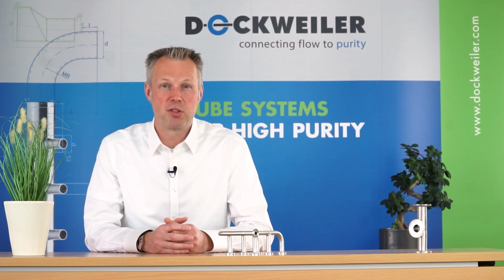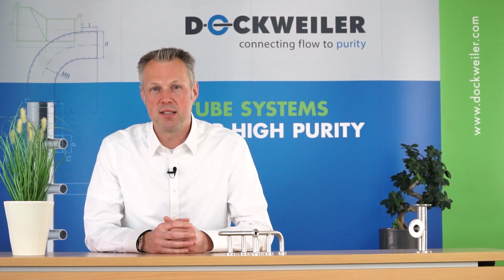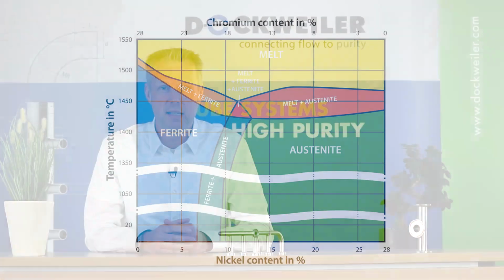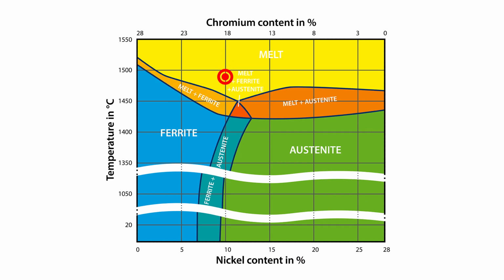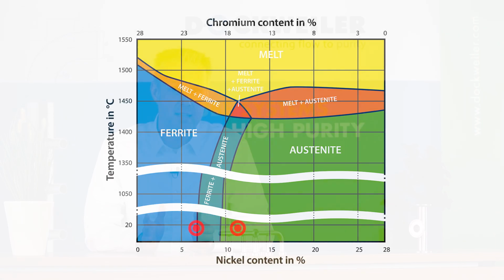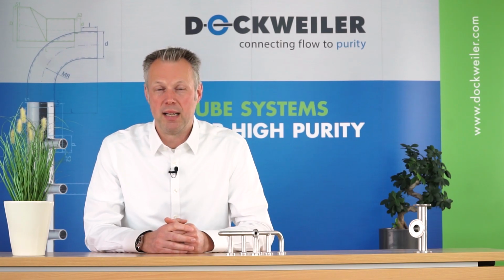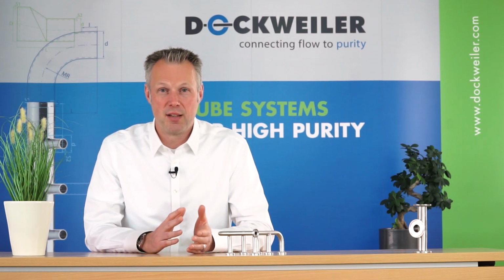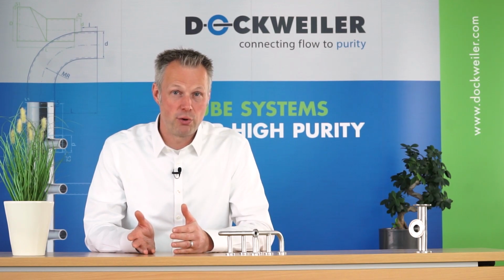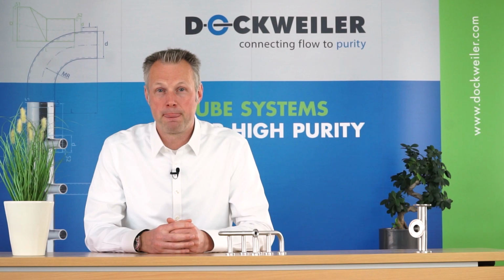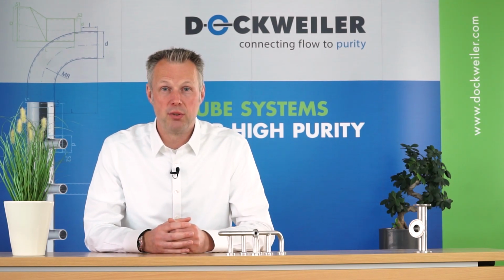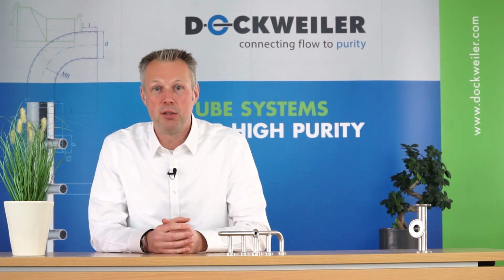We face a problem because during welding, this transition, this section, will be passed in just some tenths of a second. So the temperature transition from 1500 degrees to 1300, 1200 degrees will be done in some tenths of a second only. And therefore, those ferritic crystals cannot dissolve and transfer to the austenitic structure anymore. So you need to help the material. You need to do something to move the atoms, but maintain the mechanical stability of your system.